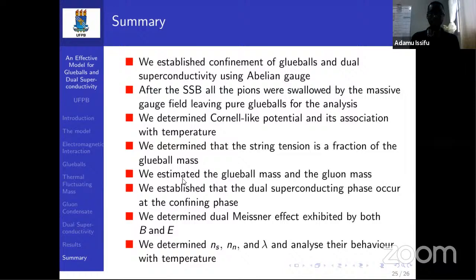We estimated the glueball mass and the gluon mass from our model framework. We also established that the dual superconducting phase occurs at the confining phase. That is in the region where we have higher glueball condensation. And then we established a Meissner effect exhibited by both the electric and the magnetic source. And then we determined the superconducting monopole density and the normal monopole density, and then London penetration depth, and analyzed their behavior with temperature.